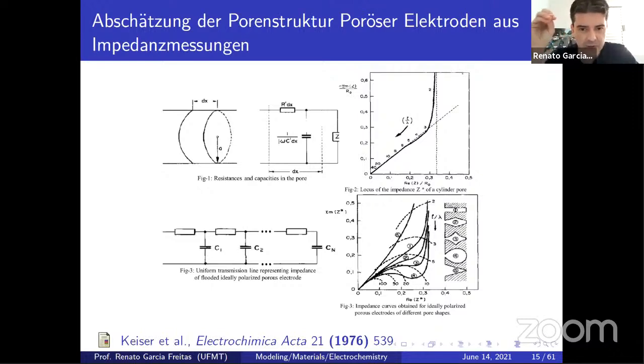We are paying attention to high frequency because at high frequency we see the 45 degree increase from the transmission line pores. Many of you probably have high frequency and 45 degree slopes and don't know how to use the transmission line. Unfortunately, I see people just delete that part. If you delete the 45 degree transmission line part at high frequency, you have an equivalent circuit for sure, but unfortunately we are making an underestimation of your system. We have a very fruitful system to study, and you just cut the part.